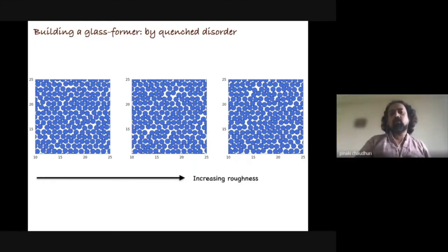So basically, if you go from left to right and look closely, with increasing roughness of this underlying potential, this local hexagonal order starts getting broken apart. If you compare the image on the left and the image on the right, you can see that these hexagonal motifs are now breaking apart as you go to increasing and increasing roughness of the underlying potential.